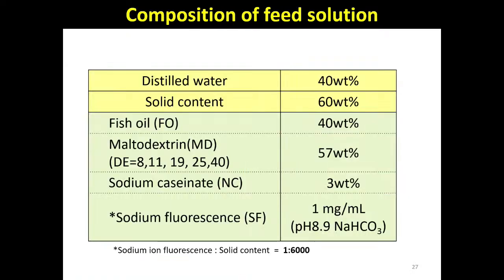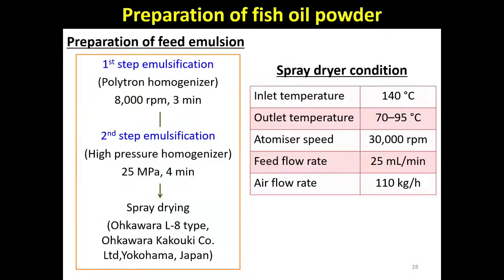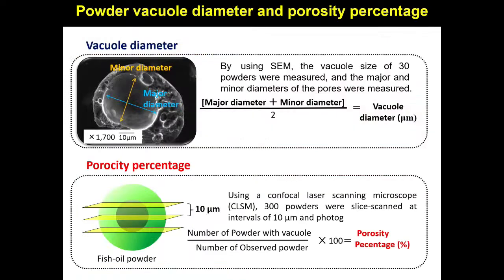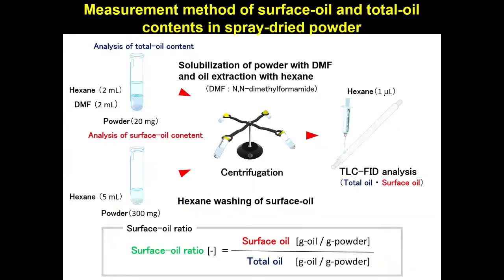So for the preparation of the fish oil powder, in this case, we homogenize those solutions. The first emulsification uses a mechanical homogenizer, and the second emulsification uses a high pressure homogenizer. We get a small oil droplet or large oil droplet feed solution. And then after spray drying, we check the vacuole size, the powder size, and the vacuole percentage. And then we measure the surface oil content by some method. Surface oil ratio means the surface oil, not encapsulated, divided by the total oil in the powder.